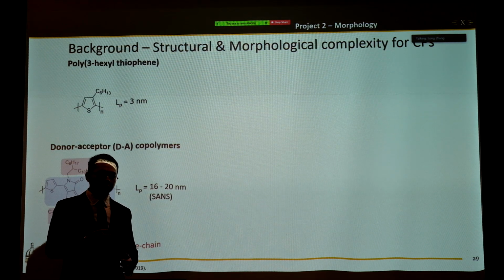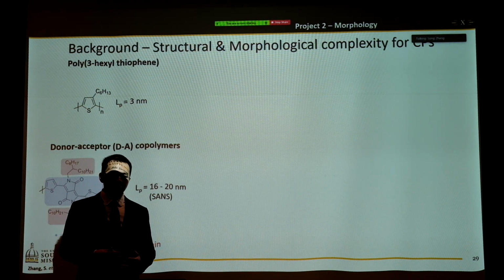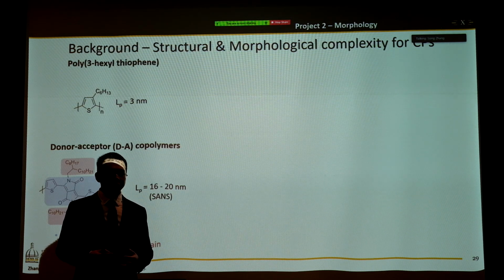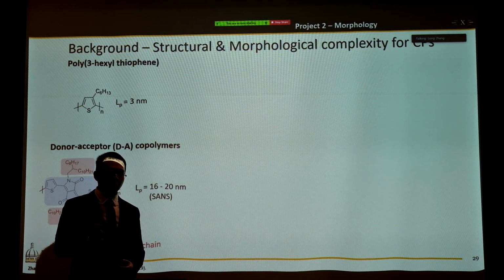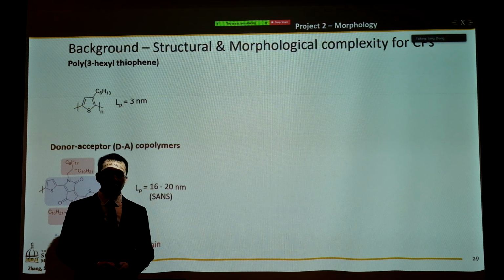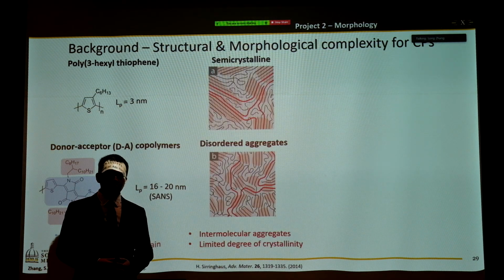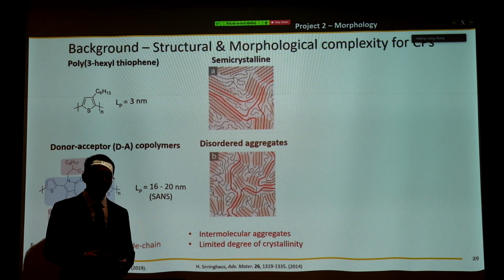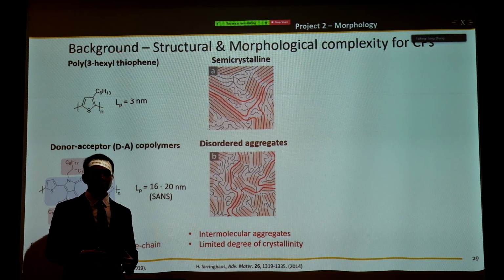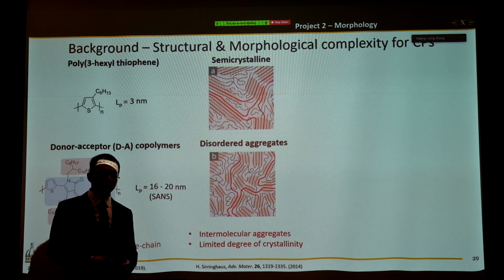Okay, to start with, I want to introduce some of the complexity in the structure and morphology of these donor acceptor polymers. So polyethylene, a traditional polymer, typically has a persistence length of around 7 to 9 angstroms, while P3HT is 3 times more rigid in the backbone, and donor-acceptor polymers are 6 times more rigid than P3HT. That's why in the thin film morphology, they are very different. For example, polyethylene and P3HT can sufficiently have this chain folding behavior in the crystalline domain.